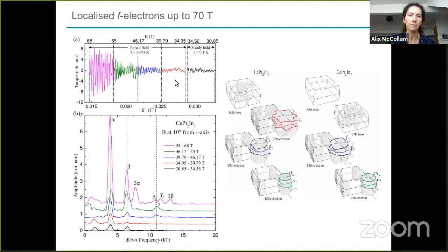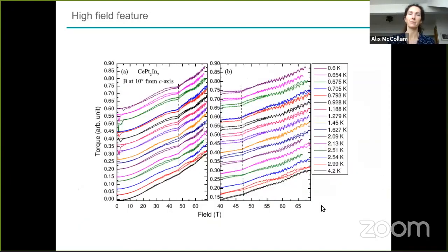So these are examples of the data across that field region. This is the highest field, this is 1 over B, and this is the lowest field. And these are the Fourier transforms giving us the frequencies, so the areas of the Fermi surfaces, the alpha, beta, gamma. They're unchanged over this region from 30 to 35 Tesla up to 50 to 60, 70 Tesla. This gamma frequency splits a little bit, but it's unchanged. We don't see it at very low field. And these ones don't shift and they're unchanged. So we say that the f-electrons are localized up to 70 Tesla.